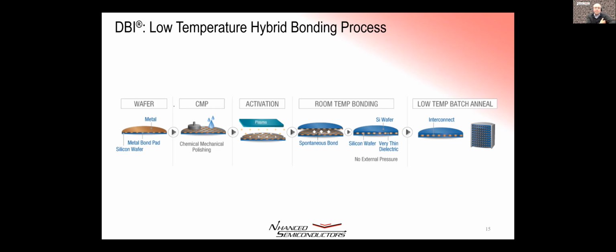I didn't put the film in today to show it, but it's in real time. You can actually see the bond wave propagate if it's a glass wafer on the top. After that, we anneal it, and once the annealing is done, it's permanent. We actually do a check to make sure that the alignment was good before we do the anneal. And if the alignment wasn't good, we can take the wafers apart and do a touch polish, we call it, to clean up the surface, reactivate it, and bond them again.